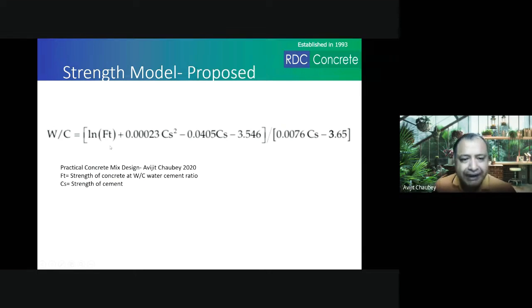Just do a trial with any water cement ratio, say 0.5. You make the concrete, find out its strength, and calibrate this equation. And how do you calibrate this equation? You put the water cement ratio as 0.5, and in the place of FT, just put the strength of concrete that you got. So let us say with 0.5 water cement ratio you got a strength of 25 MPa. So put 25 over here, 0.5 over here, and find out the value of CS. CS is the strength of cement. Now, once you have found out the strength of cement, you can predict the strength for other water cement ratios.